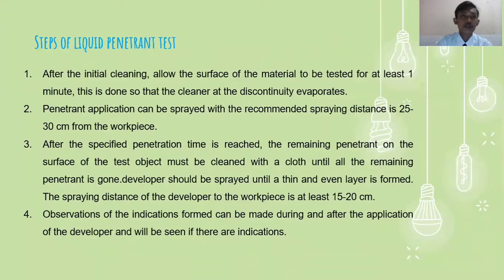Steps of the liquid penetrant test. Number one, after the initial cleaning, allow the surface of the material to be tested to rest for at least 1 minute. This is done so that the cleaner at the discontinuity evaporates. Number two, penetrant application can be sprayed with the recommended spraying distance of 25 until 30 centimeters from the workpiece.